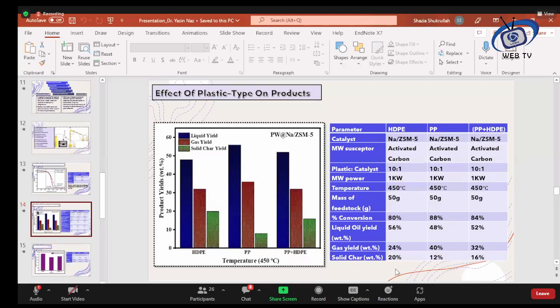So these findings suggest that if our focus is on the liquid and the solid product, we should prefer HDPE material in the microwave pyrolysis, and if our focus is on the production of gases, we should choose PP because it gives us 40% gas, which is much higher as compared to the others. And HDPE gives us 20% solid residue, which is much higher as compared to pure PP and its mixture with HDPE.